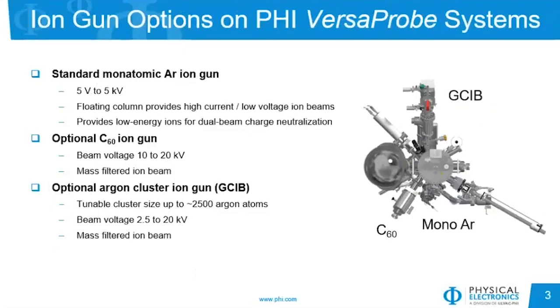And so the ion gun options that are available on VersaProbe systems are shown here. There are three ion guns that we can use. The standard monoatomic argon ion gun is standard on the system. That is used both for sputtering and also used for the dual beam charge compensation technology. That ion gun can go up to 5 kV. We can also use it in a floating column mode where we can generate large currents of ions at low voltages. We also have an optional C60 ion gun using a C60 buckyball as the ion source.